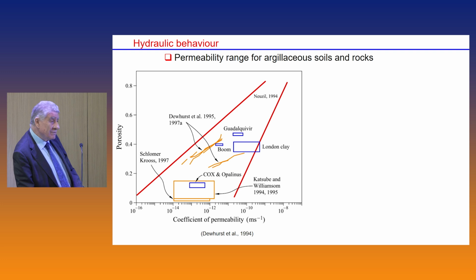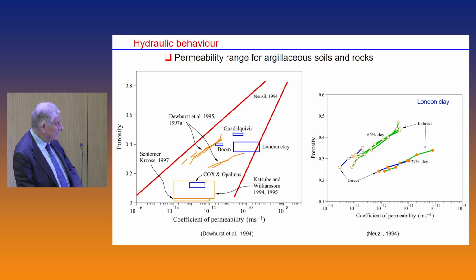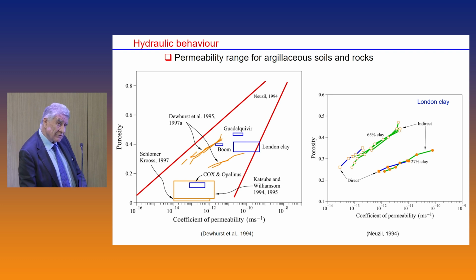It reduces with porosity, but perhaps the most significant feature to highlight here is that for a constant porosity, there may be 3 orders of magnitude difference in the permeability, which reminds us that porosity is not the important factor in this case. It's the fabric, it's the size of the pores, and so you can have quite a spread. For instance, this is again London clay taken from 2 different layers with different amounts of clay and different fabric, and you can see there is, for the same porosity again, a couple of orders of magnitude of difference in the permeability, which is always quite low.